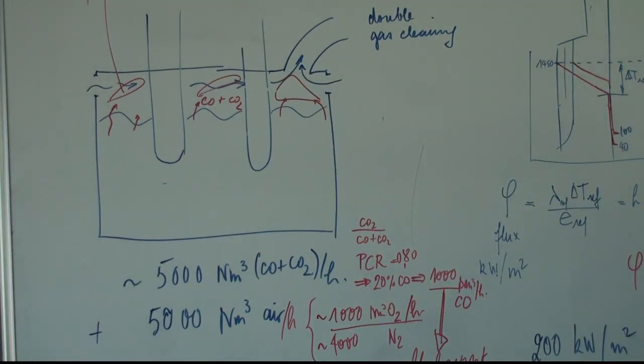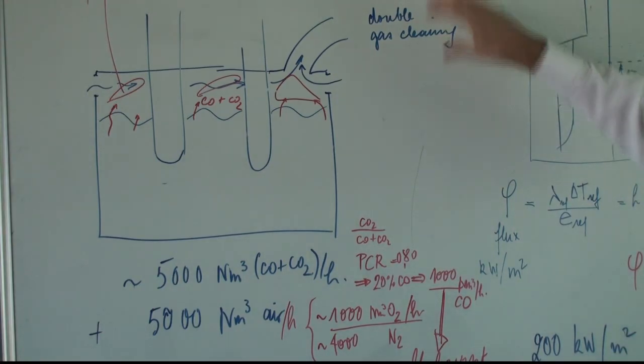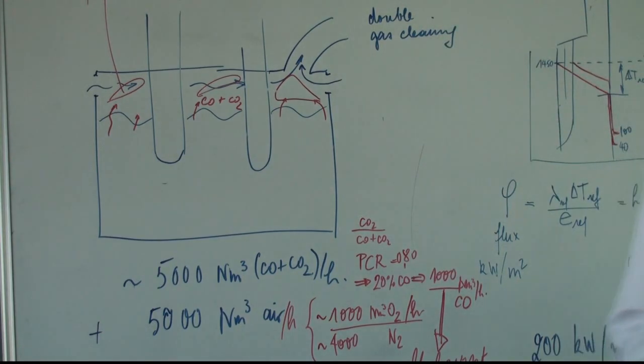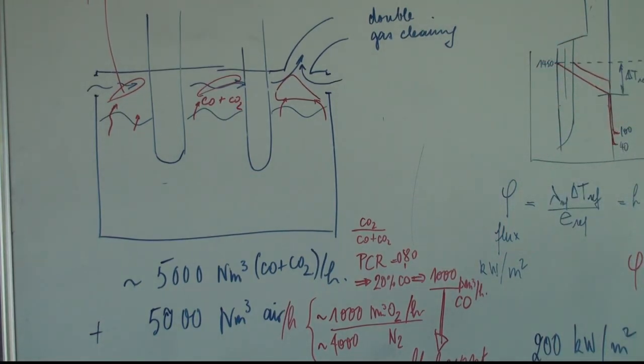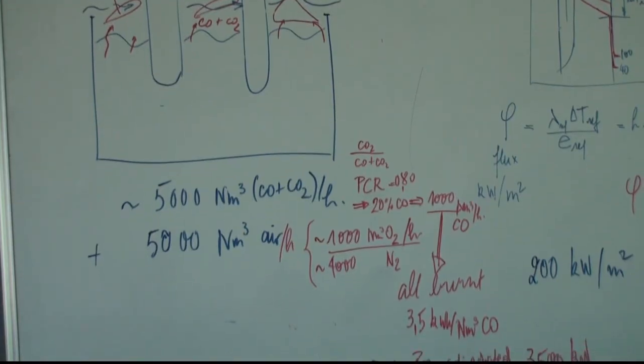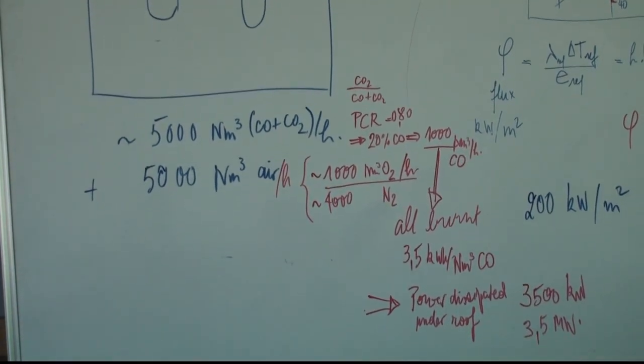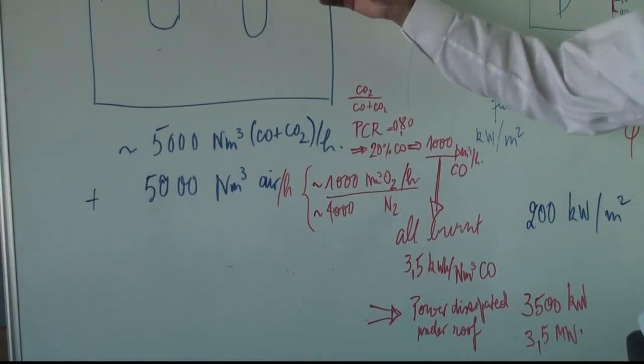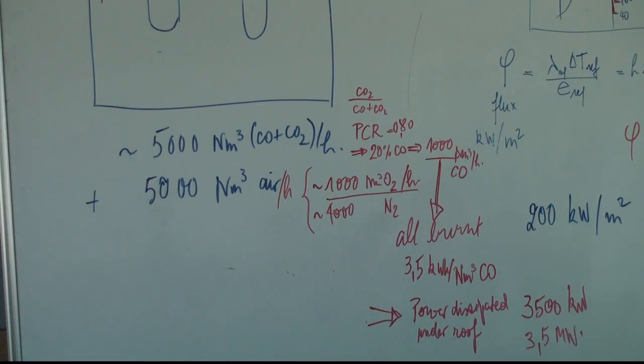Then what about if CO is not burned? Anyway, CO must be treated afterwards. Yes, of course. You will have a post-combustion chamber anyway. You must have this anyway. But it's better to burn it in the post-combustion chamber. But does it have any impact that the ore, raw material, can be heated up due to the CO burning? That's true. It can be heated up a bit, yes, a little bit. But the problem is that overheating of the roof is not good.